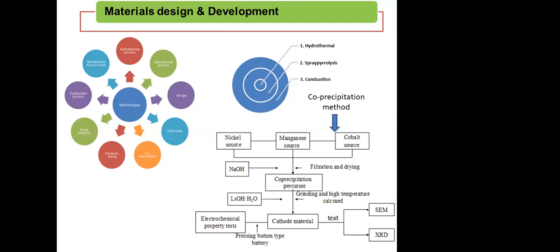Here I have shown in a pictorial diagram the co-precipitation method for making NMC. You need a nickel source, manganese source, and cobalt source. All these three salts of nickel, manganese, and cobalt need to be precipitated with NaOH or ammonia solution. Once the precipitate has come, it has to be filtered and dried. After drying, it has to be ground, and then we need to add lithium hydroxide or lithium carbonate. Generally, for NMC synthesis, that is lithium nickel manganese cobalt oxide, lithium hydroxide is the right choice. But for lithium iron phosphate, lithium carbonate is the good choice for making cathode actives.